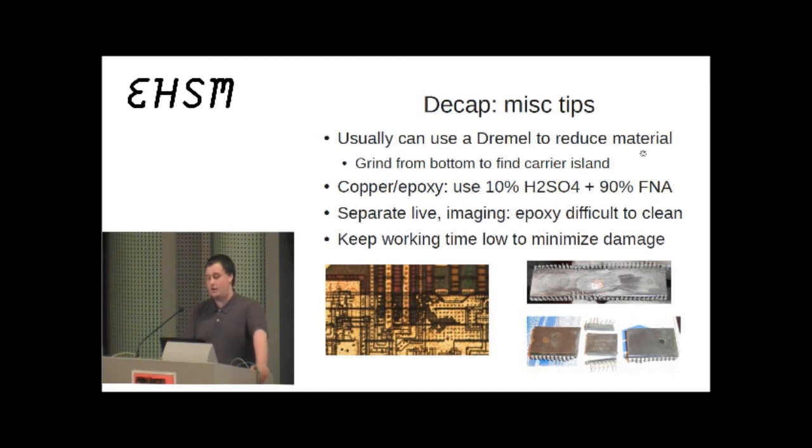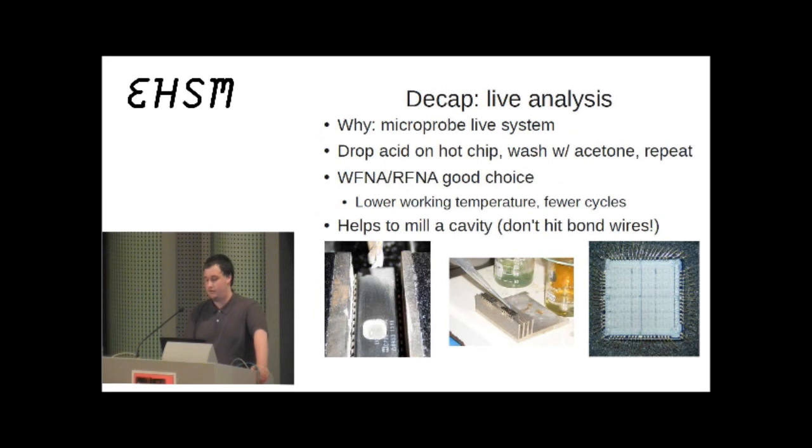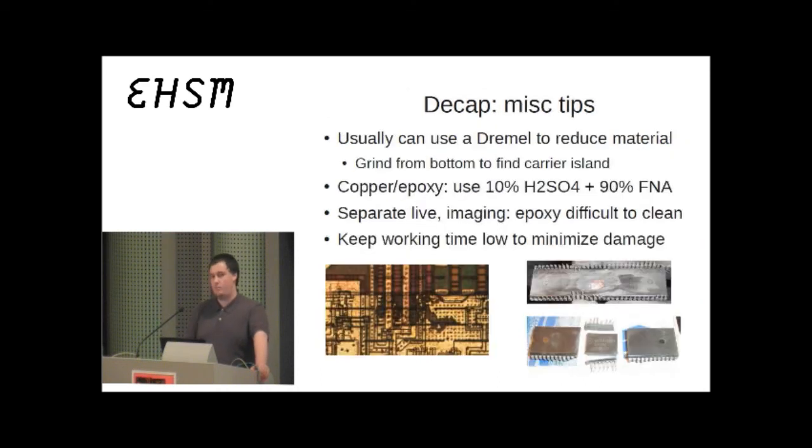Also, if you have a chip that you would like to be able to microprobe, I would suggest that you try to get two samples if possible. While they're still in the packages like this, each time you clean it, you will keep getting runoff from the epoxy and you'll get dirty images. They might not look bad, but you'll get streaks and other little defects on the chip. So if you can, keep one for microprobing and image one separately that you can clean really well.